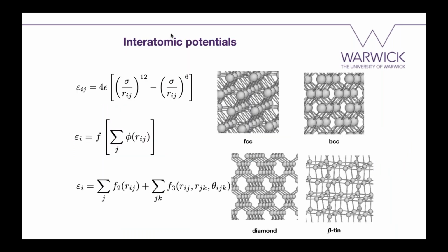To introduce this, I want to start from the interatomic potentials. These have in the past been characterized by some closed functional form, which is motivated by some physical knowledge of the system. The simplest of these could be the Lennard-Jones model, which is based on our understanding of how pair interactions work for noble gases, but it turns out also to work for some metals. The problem is that this physical understanding breaks down in different atomic arrangements. For example, if we go from an FCC to a BCC type of metal, it cannot be represented anymore by this simple pair interaction. So we need to put in more physics.